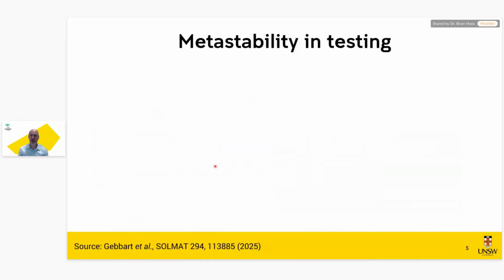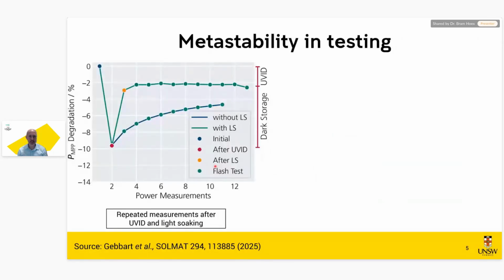A major concern for UVID is that it's metastable. If you do the typical stress testing, then put the samples away after stress testing and measure them after a few days, which is quite common, you see that your measurement shows quite severe power loss. But it can actually be improved by light soaking, and it can be improved by just measuring several times. So this just indicates a metastability.